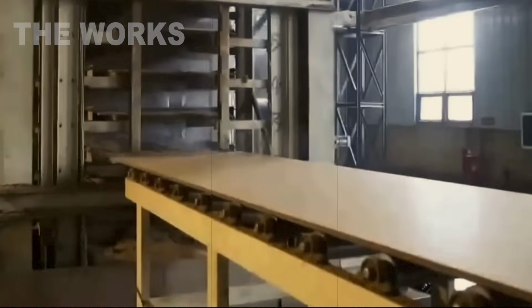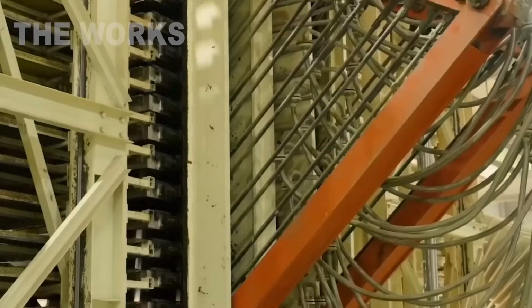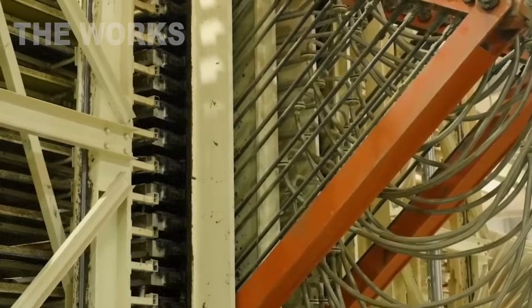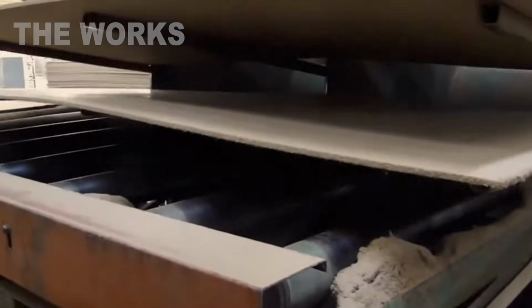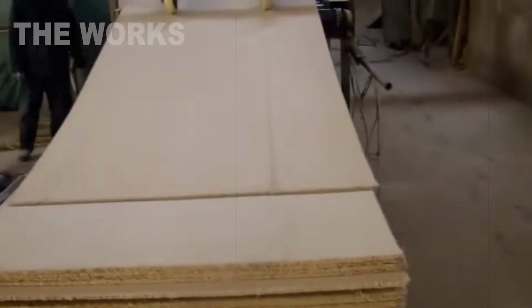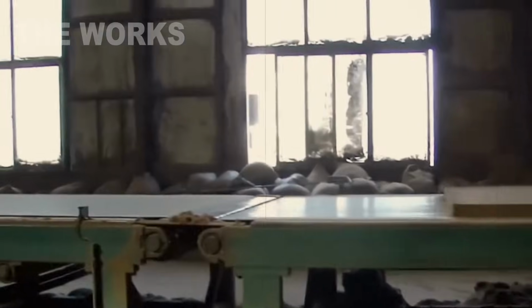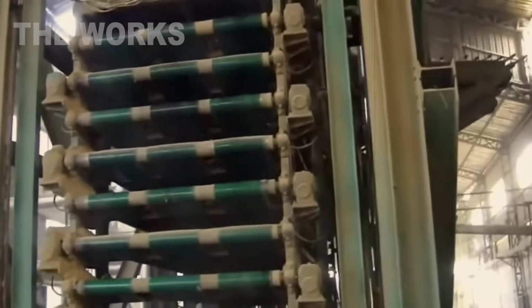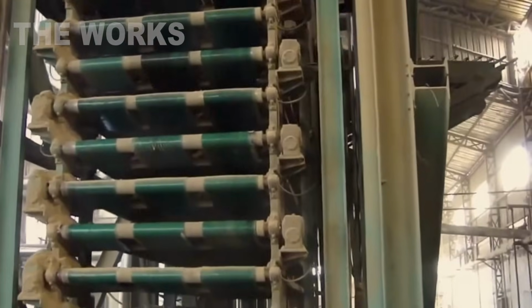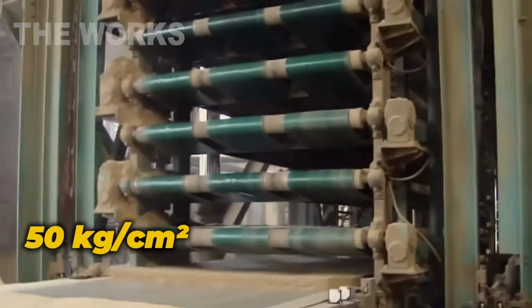It activates the resin, causing it to polymerize and bond the fibers into a single monolith, and simultaneously evaporates any remaining moisture, which escapes from the board as hissing steam. After just a few minutes in this steel embrace, the loose mat transforms into a solid, dense, perfectly flat, and still very hot MDF board. Pressure in modern presses can reach 700 pounds per square inch. Imagine an adult cow standing on an area the size of a postage stamp.